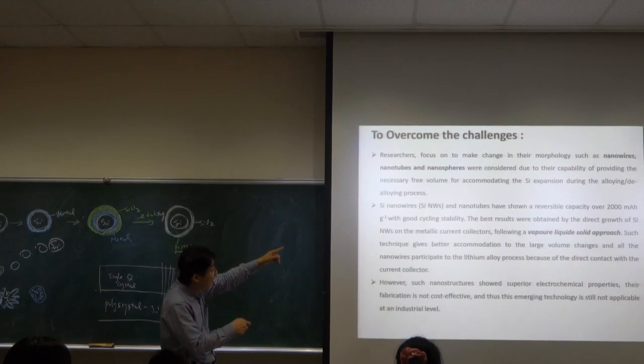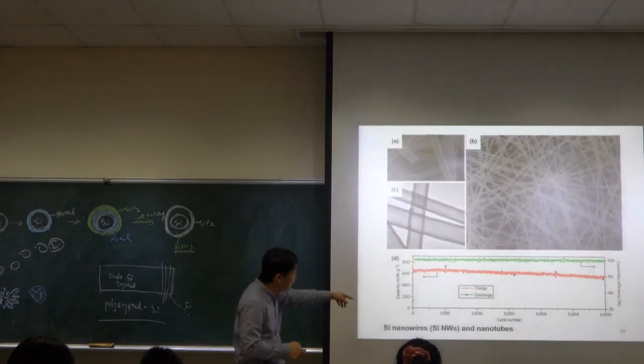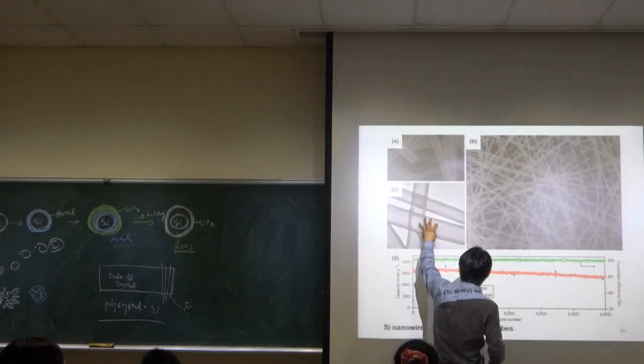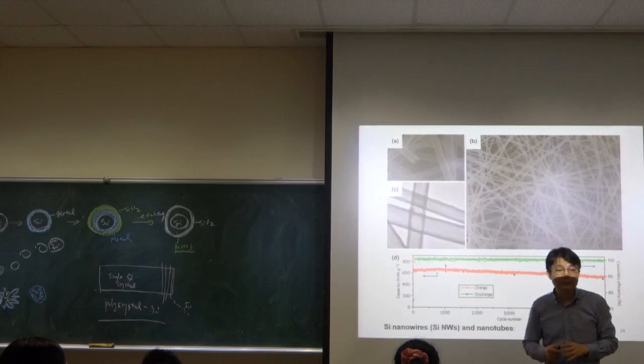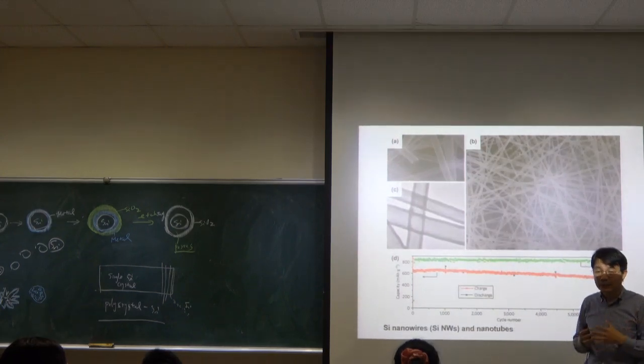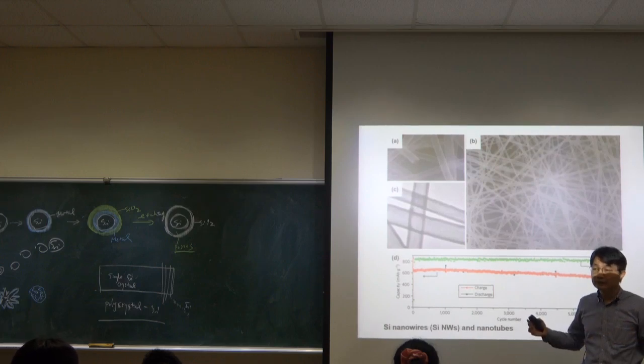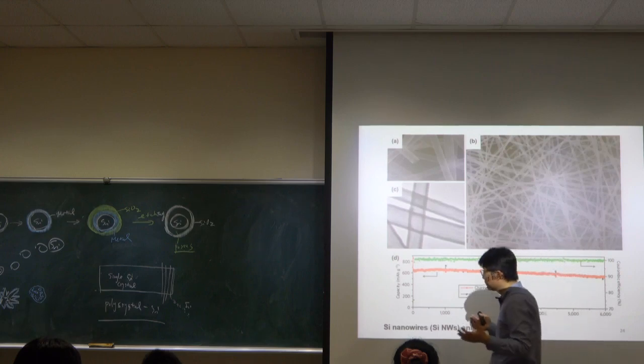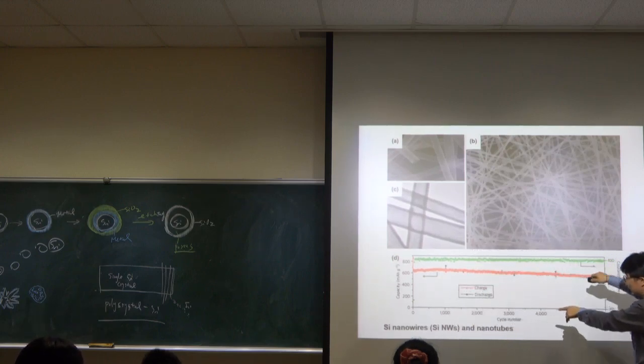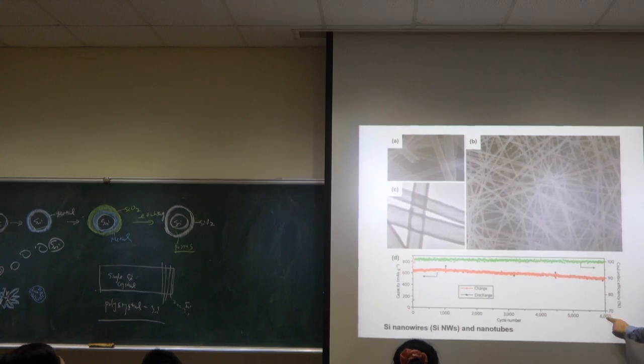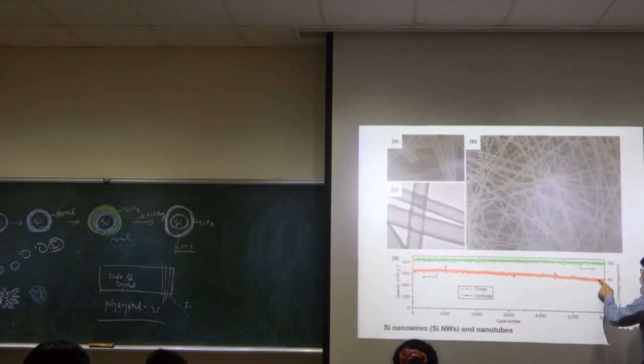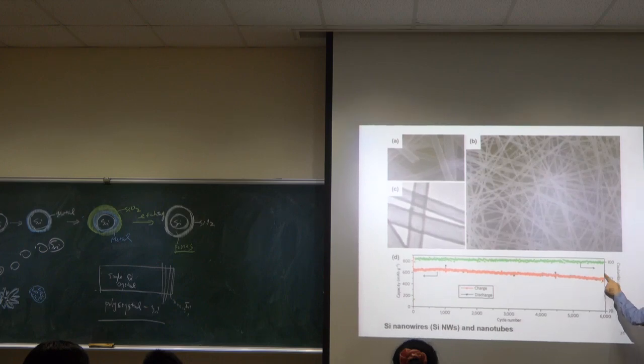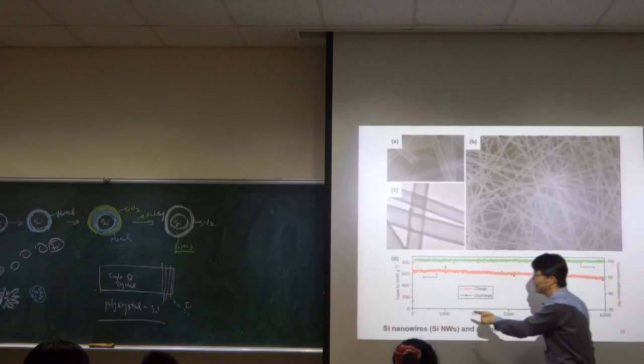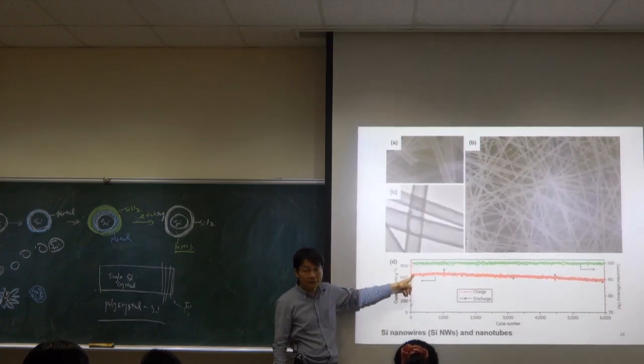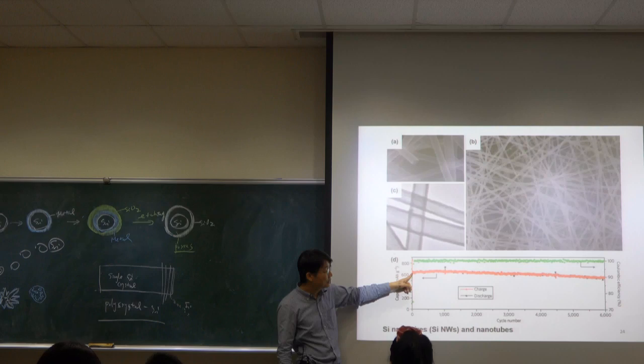Because of the nanowire and nanotube, you can see here is quite good. This is nanowire, and inside they can make the silicon nanotube, right? By using some methodology like chemical solution or thermal evaporation. So you can see the charge and discharge here is 6,000 cycles. Charge and discharge always maintain coulombic efficiency at 90%, right? You can see the first cycle is right here, 600. Of course, compared to graphite capacity, it is still low.